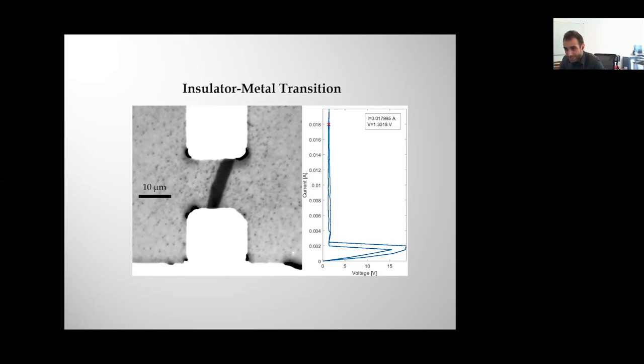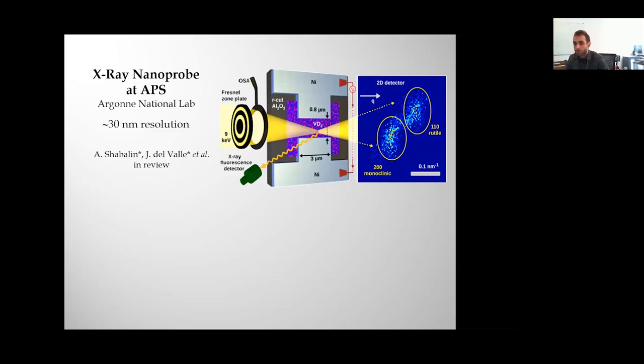And it doesn't illustrate very well what happens at the nanoscale, what happens when you look closer. And that's actually a key question because it's not very well known and it's fundamental because one of the main challenges that this type of resistive switching faces is that you fabricate two devices that are very similar. They are the same device. So one of them, for some reason, has 1 volt of threshold voltage and the other one has 5 volts. There is a lot of variability between devices. So to understand that, we need to look much closer.